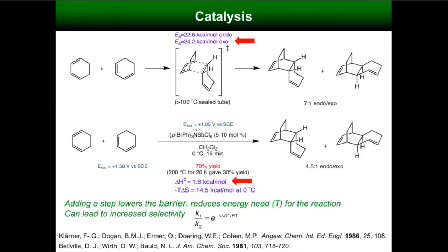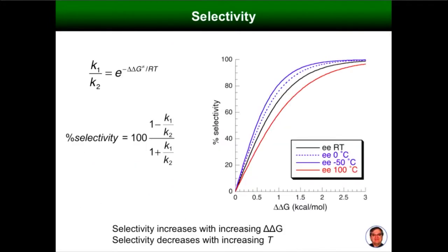So we have stereochemistry and catalysis. What is catalysis? Well, this is one example of a catalyst. If you take cyclohexadiene and heat it up in a sealed tube at greater than 100 degrees, you end up making a product. It has a relatively large activation energy. If you add a catalyst, you change the reaction pathway and the activation energy drops dramatically. Instead of needing over 100 degrees, the reaction can occur at 0 degrees, and in fact, heating it up decreases the effectiveness of the reaction. So a catalyst adds steps, but allows the reaction to occur at lower temperature. And lowering temperature allows you to increase selectivity. This is a graph of selectivity as a function of energy difference and as a function of temperature. If you decrease the temperature, your selectivity increases.